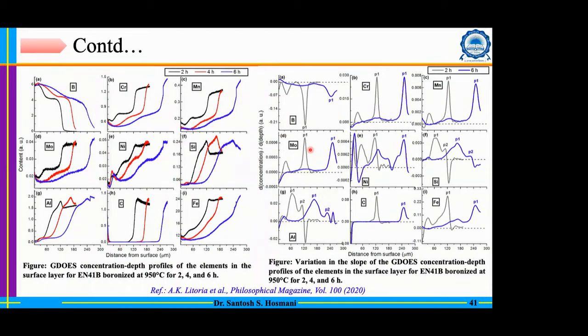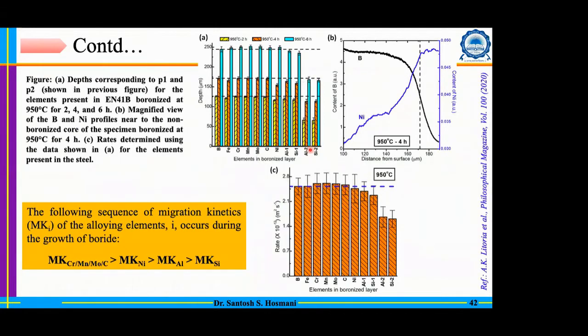We did the different duration study, and then finally we did a kinetic study there. And then we proposed the rate of the boride migration as well as the migration of other elements. You can see this horizontal dashed line in figure C is related to the boride migration. Boride migration is more or less the same as the migration kinetics of elements like chromium, nickel, manganese. Nickel is slightly less, and it is very severe for aluminum and silicon. So the migration kinetics of aluminum and silicon is extremely low.